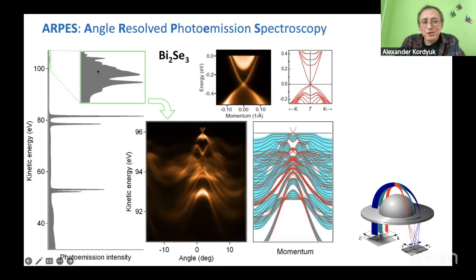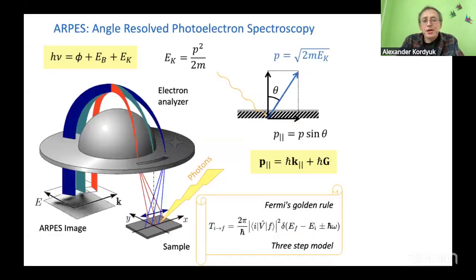But it is more important that if you can resolve not only energy but also momentum, or the angle at which the electron escapes the solid, then you have something like this, and this is the electronic band structure. People long ago managed to calculate the electronic band structure and to understand it in terms of solving the Schrödinger equation for electrons in a periodic potential. But that it is a real thing, not a theoretical concept, became clear only when angle resolved photoemission spectroscopy appeared. And it is a simple experiment to understand because you have a sample. It should be a single crystal sample because, of course, to have this structure, right? Not integrated over all directions.